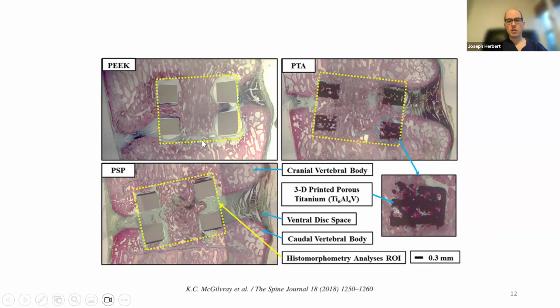And you see the PEEK. So there's through growth of the PEEK because of its macro structure. It's got a big hole in the center of it and allows bone to grow through it. But you see where the PEEK actually is itself, the bone is not adhering to it, it's not growing through it. PEEK, like titanium, is extremely biologically inert, which is, again, one of the reasons why we use it. But I think it's also a key characteristic that can be improved. So when you look at this porous titanium implant here, you see not only has growth through the middle of it, through the macro scale modification of this implant, but you can actually see on a micro scale, the bone is actually growing into this 3D printed porous titanium.